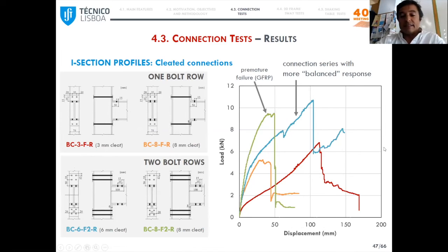So as expected, the thickness of these steel cleats had a significant influence not only in the stiffness and strength, but also in the ductility. So for thinner cleats, the stiffness was quite low, and the response was highly nonlinear because they started to yield for quite low levels of load. While for thicker cleats, although the response was stiffer, we also obtained premature failure modes in the GFRP material. So finally, the option was to adopt intermediate thickness cleats because the response were more balanced.